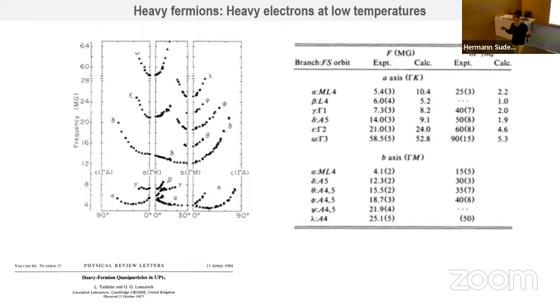So essentially with this, you can have a nice picture to work with, which is, okay, I have a system with very strong electron correlations, but when I go to low enough temperatures, I have practically the same as in a free electron gas, but I have to renormalize the mass. And this happens very nicely. So you can have really a Fermi liquid in some situations. And just for those of you who know, you don't only have a renormalized Fermi mass, but you also have a Wilson ratio which is close to one. So you can even kill the magnetism, as the Wilson ratio is related to the magnetism.